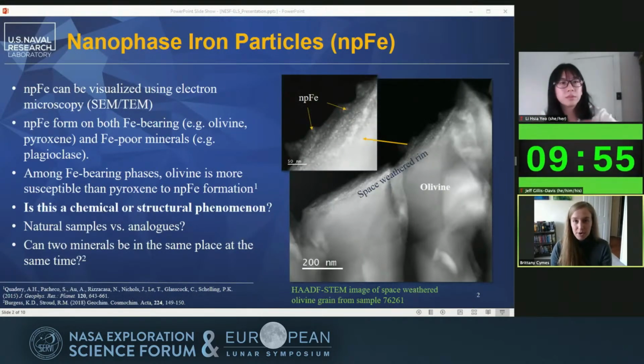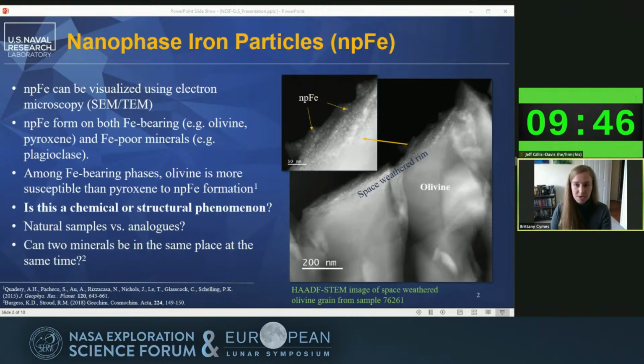Nanophase iron particles are a frequently encountered product of space weathering on lunar material, as Jeff mentioned, and I study these particles and other space weathering phenomena using transmission electron microscopy, or TEM. To give you an idea of what nanophase iron particles look like in the TEM, to the right here is a dark field image of an olivine grain acquired on our STEM instrument. At the edge of this grain, you can see a space weathered rim. And upon close inspection of this rim, you can see it's full of nanophase iron particles.